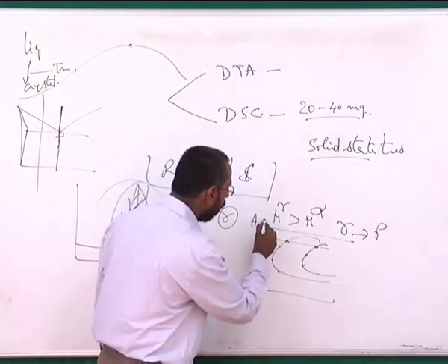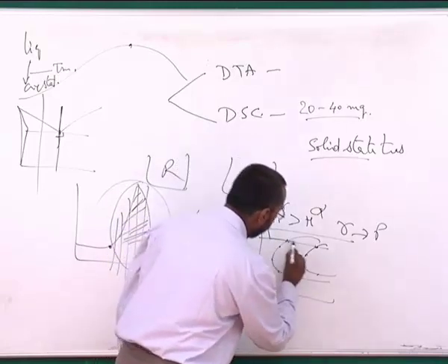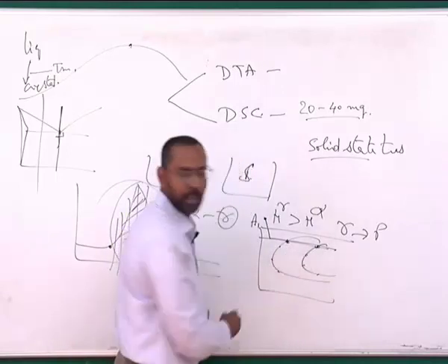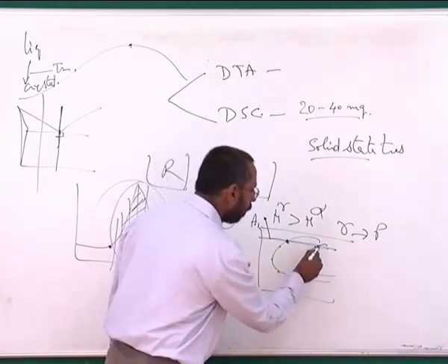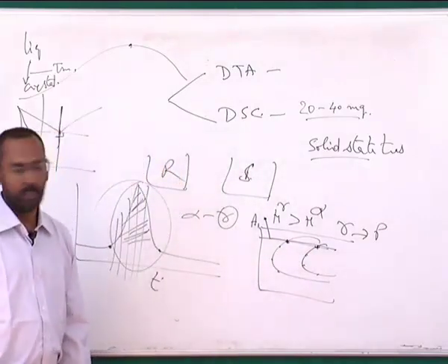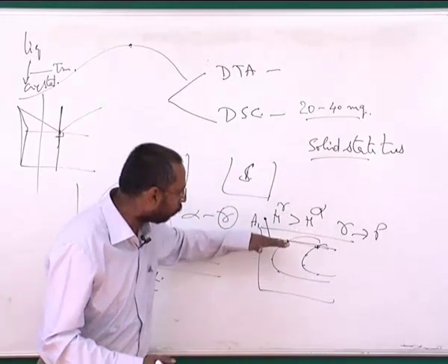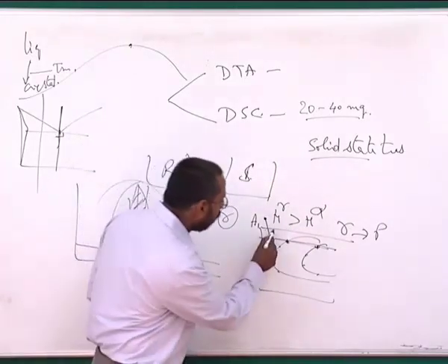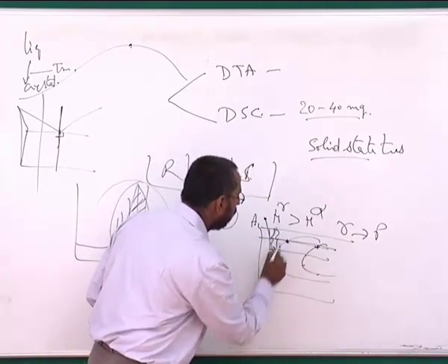So I take the alloy above the A1 temperature, quench it to this temperature and hold it there, and then find out at what time what has formed, and from this what is the time required for the start and the time required for the finish of the pearlite. So we usually take a large number of samples, hold them all, quench them to various temperatures, and what we make sure is that during this transformation, wherever temperatures I am coming, nothing has happened.